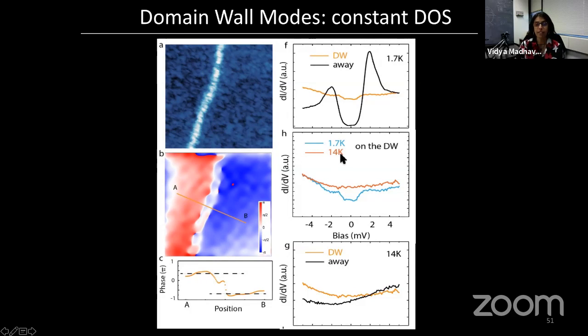And then when you go above TC, which is around 14 Kelvin, you can see that the density of states on the domain wall is flat. So this feature has disappeared. And also if you compare the domain wall density of states and the density of states far away at 14 Kelvin, they both look flat and very similar to each other.